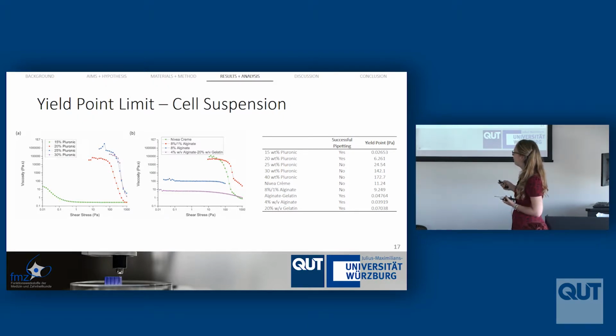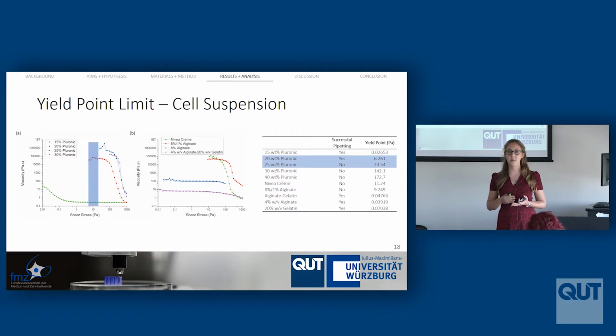Remember, we're looking for these first stable data points when the material starts to flow. And you can see for that low percentage of Pluronic here, the material's already flowing, it's basically water. As we upped that percentage, these yield points started increasing. So we can make a limit. So this is looking at the limit of the materials that could suspend cells, and then looking mathematically, what did that look like as a shear stress?